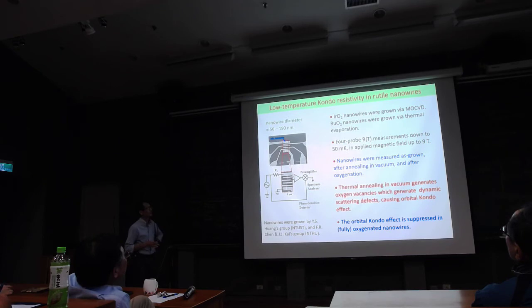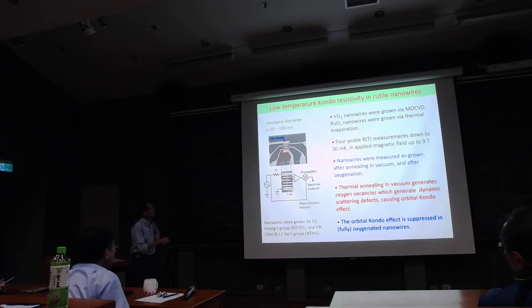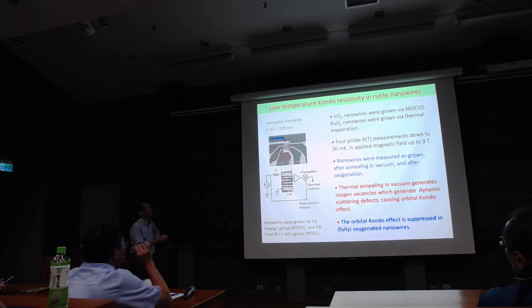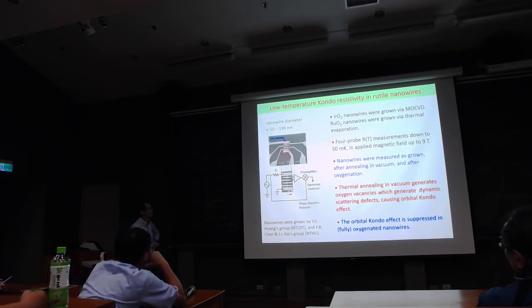So we studied iridium dioxide and ruthenium dioxide nanowire. We want to make a nanowire because then you have a larger resistivity and you can have a higher resolution. So here are our nanowires and electrodes to send in currents, measuring voltage and measurement system.